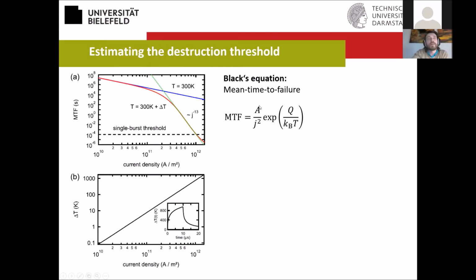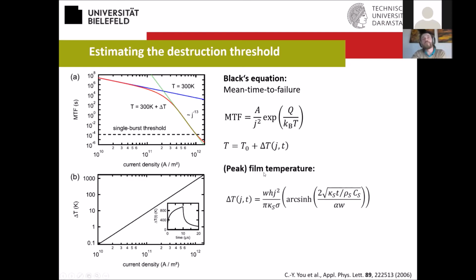Black's equation says that the mean time to failure depends on 1 over j squared times an exponential with an activation energy. So as we increase the current density, we would get this blue line here. But due to the Joule heating of our current, we need to take the additional heat in the film into account. We do this analytically with this equation from this paper, and this gives us the red line here. Effectively, this gives us a dependence on the current density of j to the minus 13. This is a very strong current density dependence for the mean time to failure for our devices. And we find that our mean time to failure is about 1 microsecond at a current density of 2 × 10^12 amps per square meter, which is very close to what we observe experimentally.